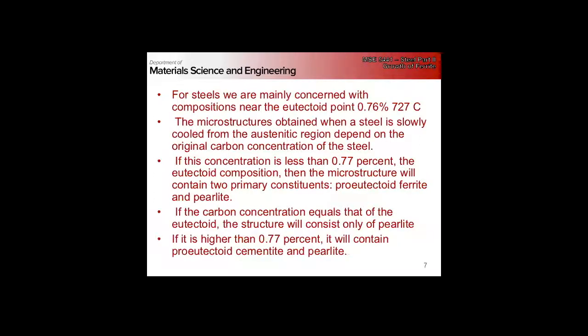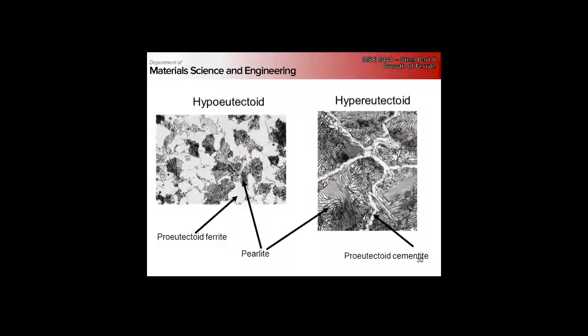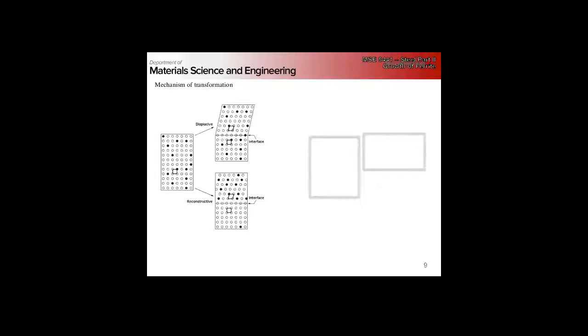We looked at structures that come from hypereutectoid and hypoeutectoid compositions. If we're light on carbon, we get regions of ferrite with pearlite interdispersed. If we're hypereutectoid, we have proeutectoid cementite that forms on the prior austenite grain boundaries, and then the rest of the prior austenite grain transforms into pearlite. We'll be talking a lot more about pearlite on Friday.